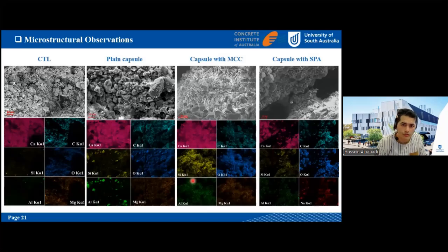In terms of the microstructural analysis, the most dominant product generated inside the crack was calcite, calcium carbonate, in the control samples. But in the capsule incorporated samples, apart from the calcites, we had a lot of aluminum bearing phases like aluminum silicate hydrates, like very thin particles within the calcite particles.